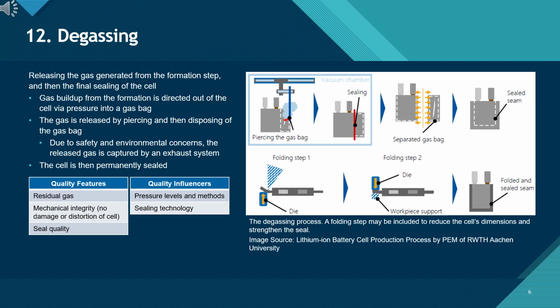Once the gas is released, the pouch is resealed along the seam. Some processes add 1 or 2 folding operations to reduce the pouch height and reinforce the mechanical strength of the final seal. The objective is to leave no residual gas, maintain the mechanical integrity of the cell stack, and produce a high-quality, hermetic seal. This step is critical because poor degassing or weak sealing can lead to swelling, leaks, and long-term reliability risks.